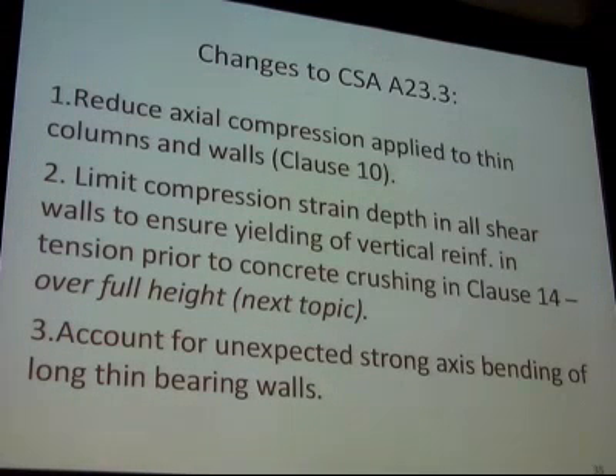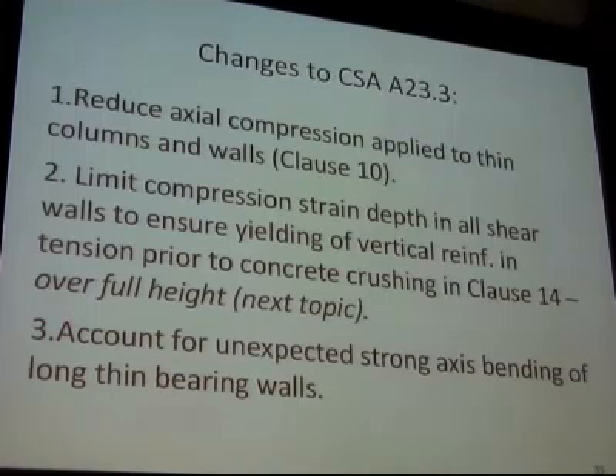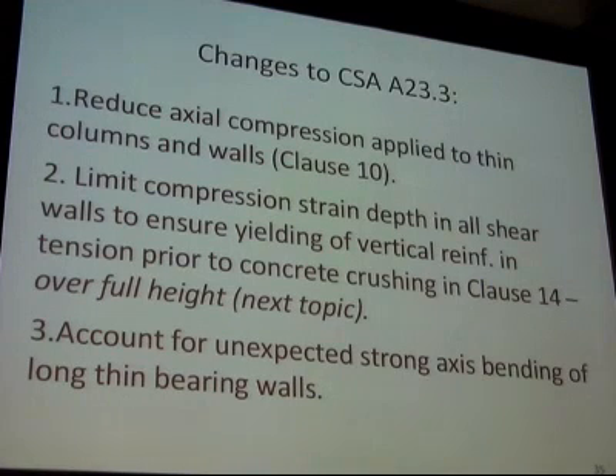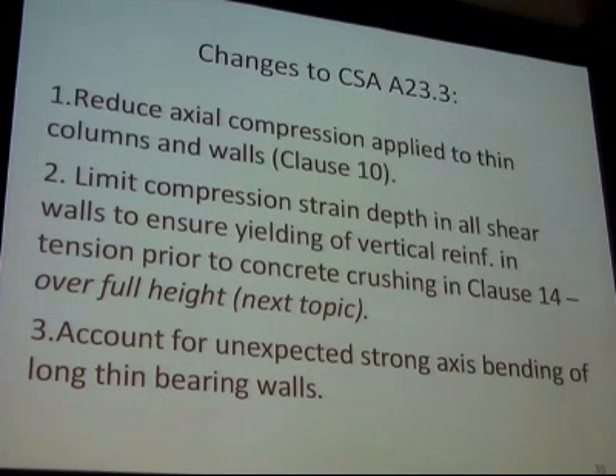Here are some of the changes that we've made as a committee to address this issue. Number one, in Clause 10, we've reduced the axial compression capacity of thin elements to reflect that failure mechanism that I just talked about. So you got thin elements that you don't want to be loading them up too high. Okay, right now people are loading them up much too high because they don't have the toughness.